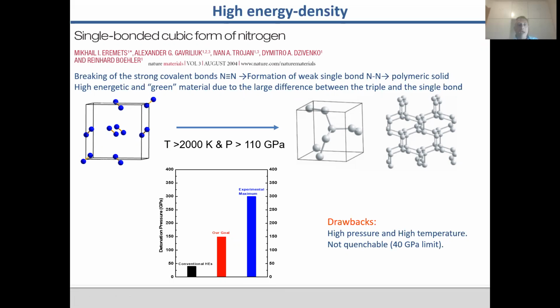So the idea here, and this is not far away from the idea of polyhydrides, which Russ knows everything about, is including an impurity in the system, trying to facilitate the formation of polynitrogen species through a binary or ternary compound. And this represents more or less this red bar here, which is, okay, can we decrease a little bit the detonation pressure, even if it is halved, still much higher, but at least be able to synthesize compounds at much lower pressure and also to be quenchable. So indeed, the idea here was to start, of course, from azides.